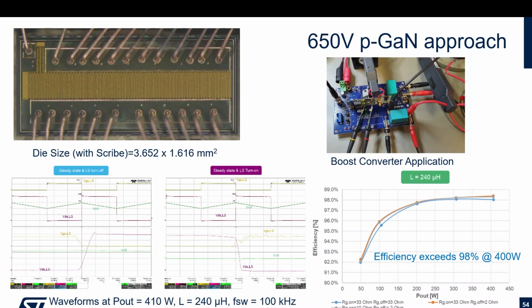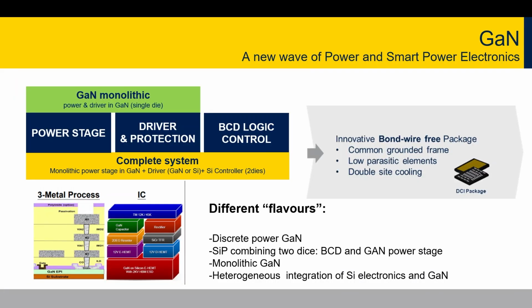We have chosen, for example, to bring to the market a device based on P-type that shows indeed the advantage that I was telling you before in the DC-DC conversion. But now, one other point that was probably mentioned in some of the questions before, and which is important, is that the lateral structure, in which the current, as you remember, flows from the source to the drain on the surface, also allows you to make some integration easily. So you can combine also with logic transistors, with depletion and enhancement transistors, so you can create monolithic GaN devices based on a gallium nitride layer on a silicon substrate.